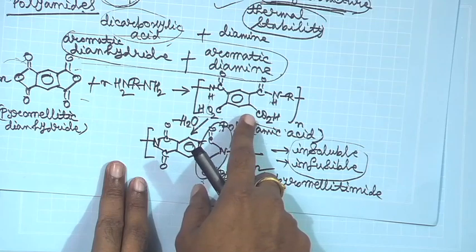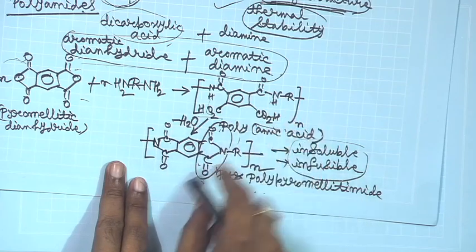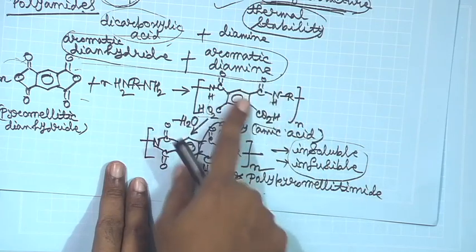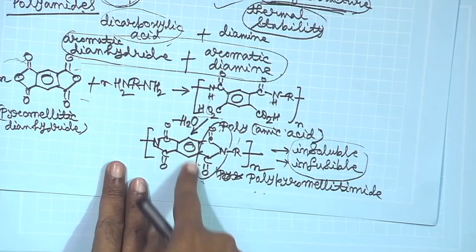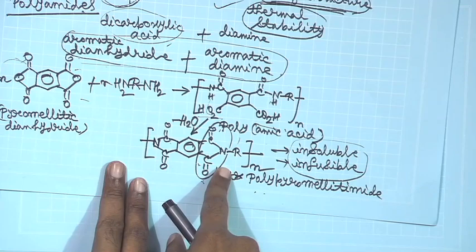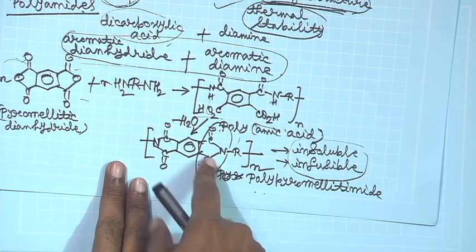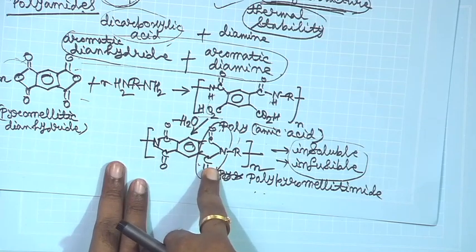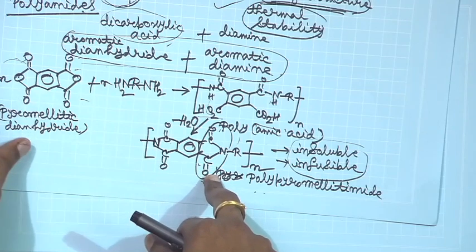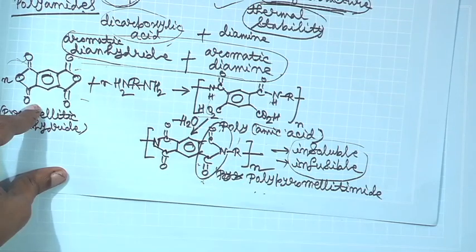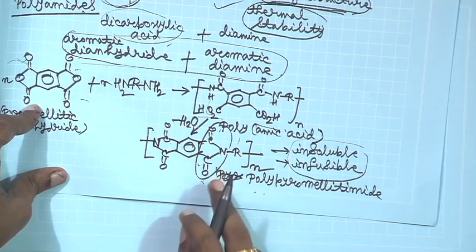But of course, one reason you now understand that you initially want to go to the desired molecular weight and then you cyclize, because if you start to prepare imide from the starting point of the reaction, if you start to target that, then the problem is it will become insoluble. It will just come out before it can form a long chain. That is the problem.